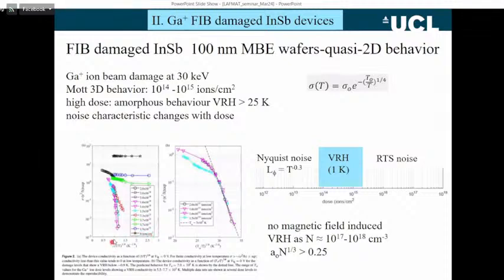So I plotted it as 1 over T to the quarter. Obviously, 1 on this scale here is 1 Kelvin. Okay, and as we put more without disorder, we just get the curve here. There's no temperature dependence. It's just an extrinsic semiconductor, slightly disordered. As we put disorder in, we find that the device conductance comes down to the quantum of conductance. It comes down to e squared over h. And then, as we put more disorder in, we start to get this exponential behavior. So the device goes over to variable range hopping.